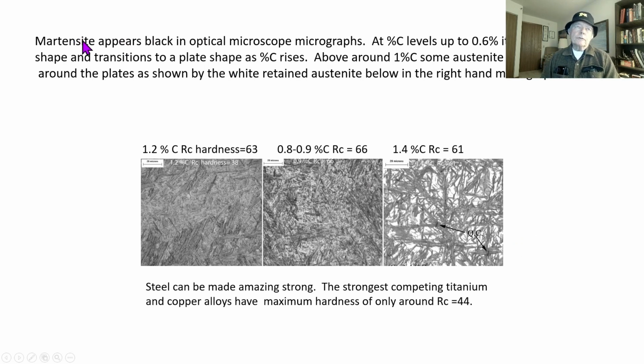In the optical microscope, martensite appears black. At percent carbon levels up to 0.6, it has a lath shape, but it transforms to a plate shape as percent carbon rises. And at around 1%, some of the austenite is retained. And you can now see the plates as shown here when you have 1.4%. Because the retained austenite etches white and the plates pop out at you.